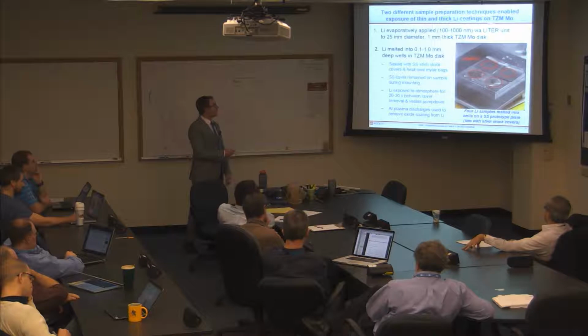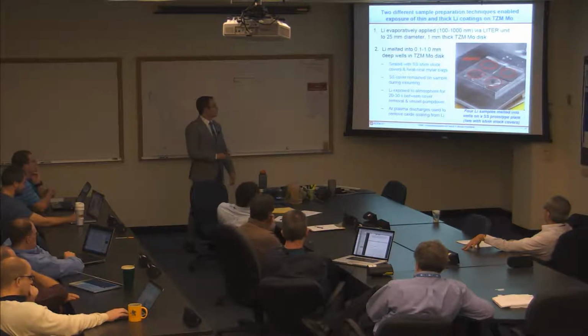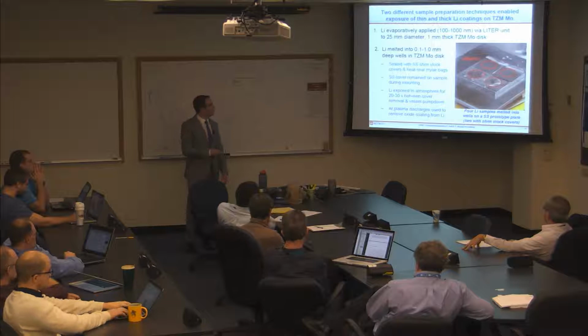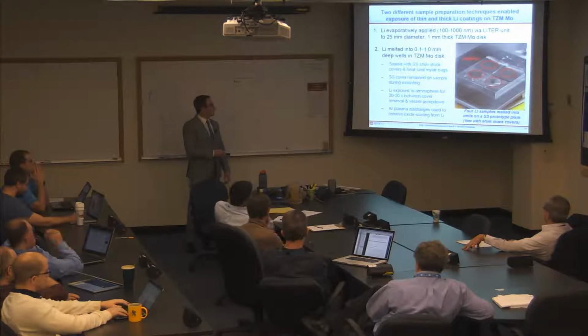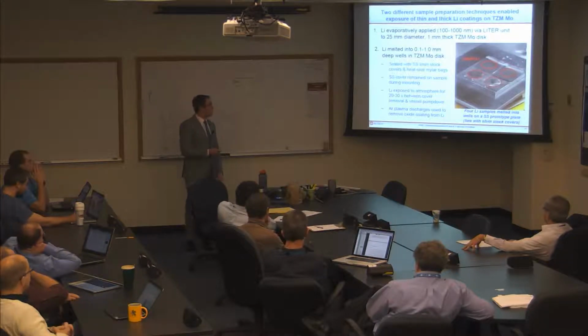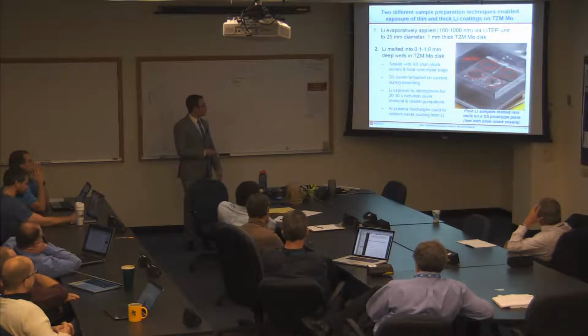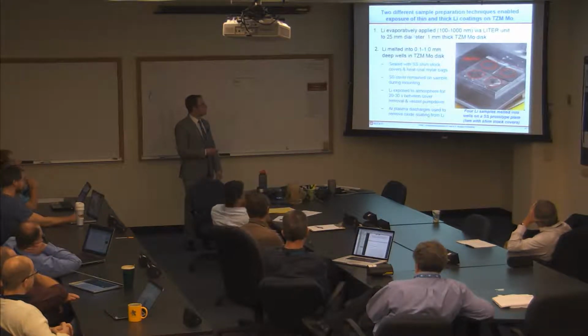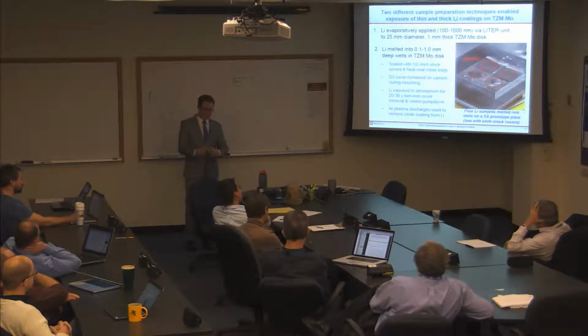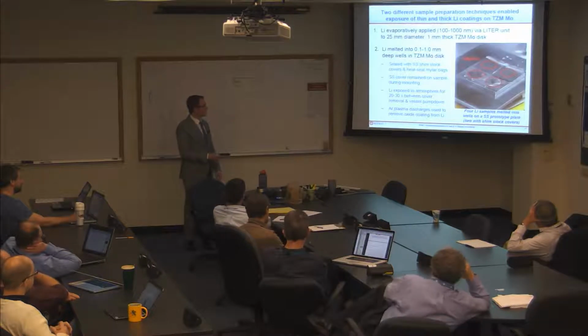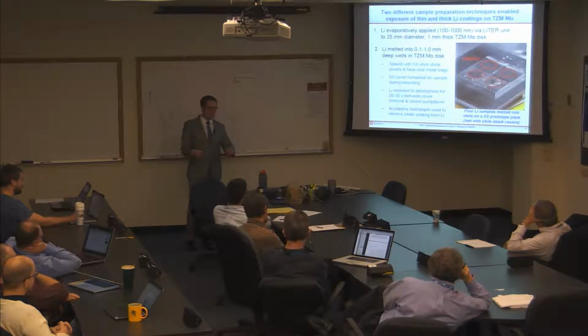So as I mentioned earlier, we have the evaporatively applied coatings that are all less than 1 micron thick. And then I'm going to talk a little bit more about this because it was a pretty novel procedure. So what we did is we melted lithium into 100 micron to 1,000 micron deep wells, so wells that were just bored into a TZM molybdenum disk. And then we put these wells into an argon glove box. We heated up the lithium to about 400, 500 C, and the lithium melted into the well.